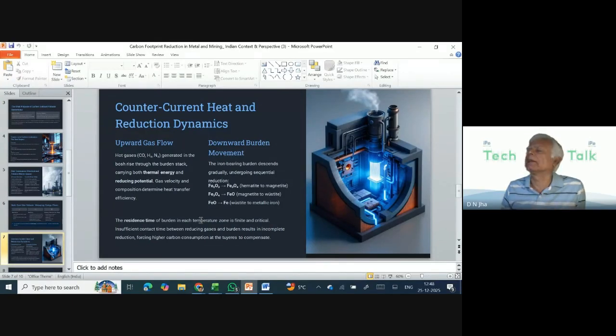This is what I said. Suppose the partial pressure or the concentration of CO is not able to reduce within the given time of travel. The burden, let's say, is traveling from the top to the bottom in 4.5 hours. Now, if it is not able to reduce, then you will have unreduced material in the hearth, and therefore you will gradually lose the temperature.